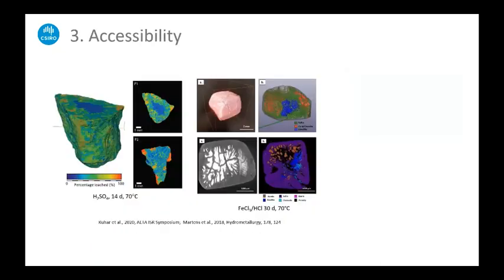And then on the accessibility side, we've looked at understanding, again at a fundamental level, what's happening to the mineral particles. So this is actually a vanadium-containing particle. We studied this particle by computed tomography scanning, so CT scanning in 3D, and then by coupling the CT scanning with mineralogy cross-sections, we were able to identify which minerals had leached and the percentage that was leached. This type of work, Belinda Godel, one of my colleagues, she's a whiz at this sort of stuff. And we could understand, for example, if you look at particle 1 and particle 2, P1 tended to leach by a shrinking core type behavior, whereas P2 seemed to leach more homogeneously. And we believe that this is related to the grain boundaries and movement of fluid along the grain boundaries.